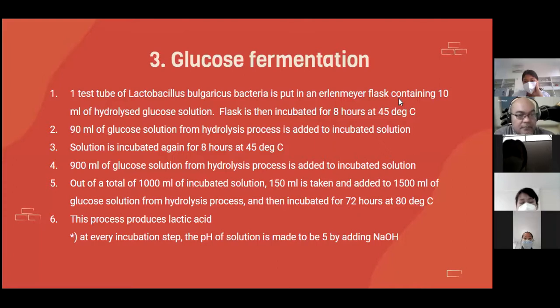And next, after the glucose is produced, it is fermented. The fermentation uses 1 test tube of Lactobacillus bulgaricus bacteria put in an Erlenmeyer flask containing 10 milliliters of hydrolyzed glucose solution. The flask is then incubated for 8 hours at 45 degrees Celsius. And then 90 milliliters of glucose solution from the previous hydrolysis process is added to the incubated solution. The solution is incubated again for 8 hours at 45 degrees Celsius. After that, the incubated solution is again added with glucose solution from the hydrolysis process. This time it is 900 milliliters. So eventually there is a total of 1000 milliliters of incubated solution.